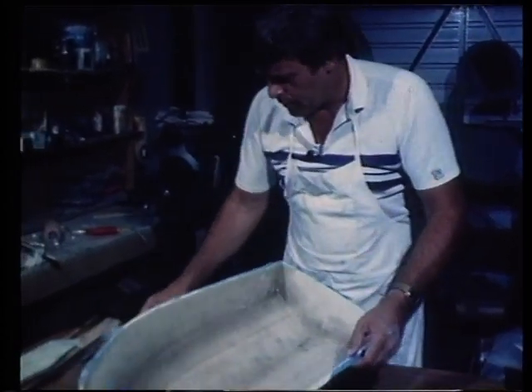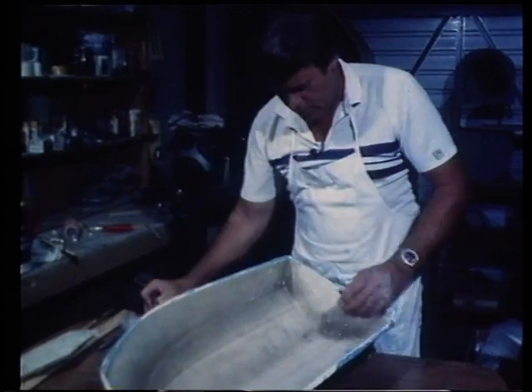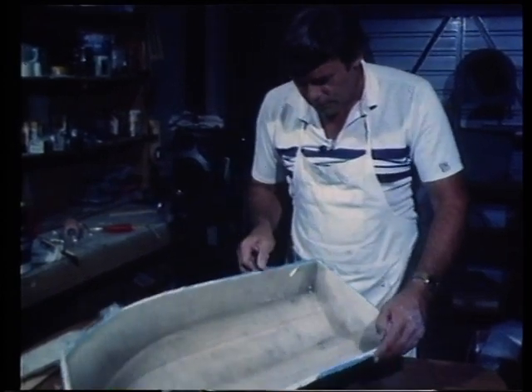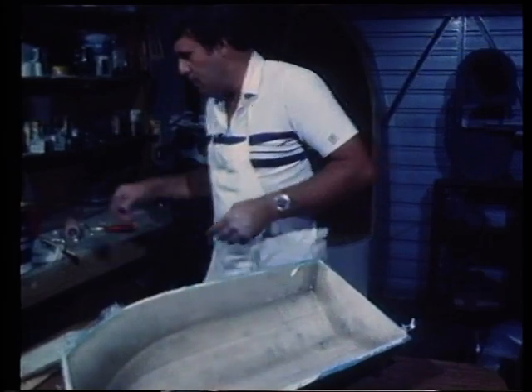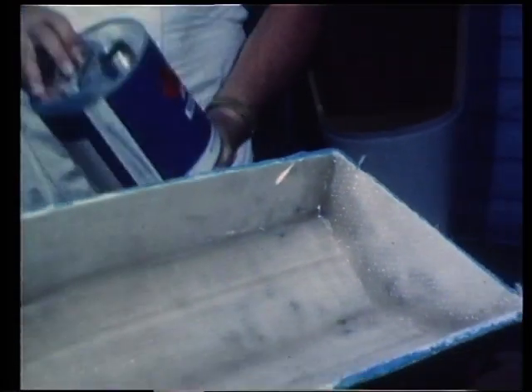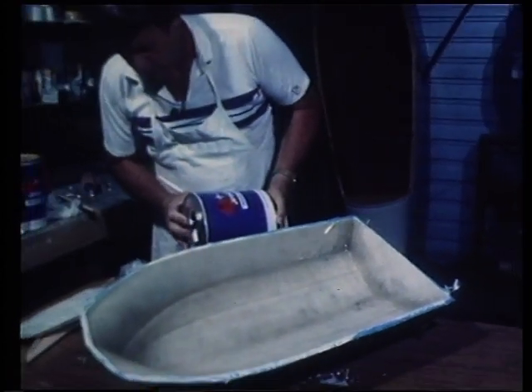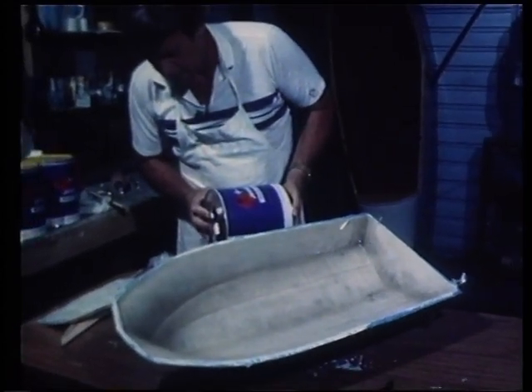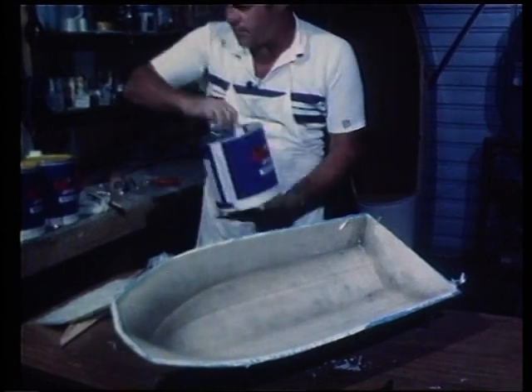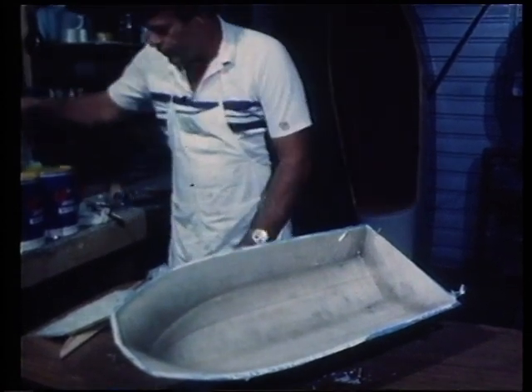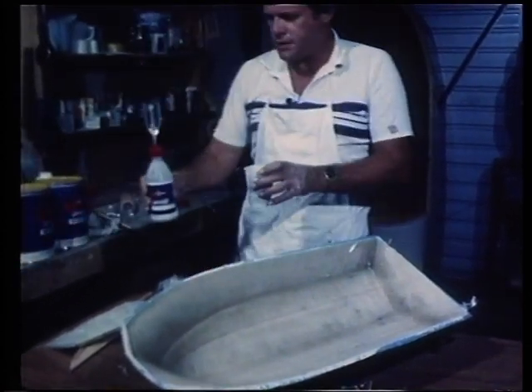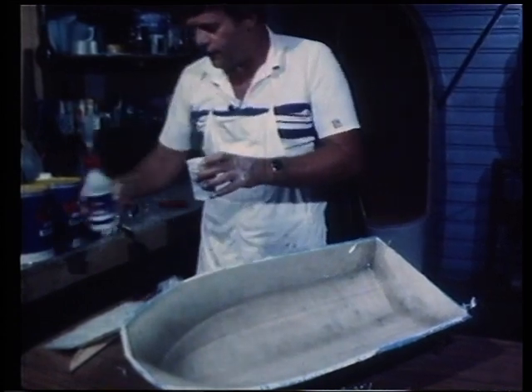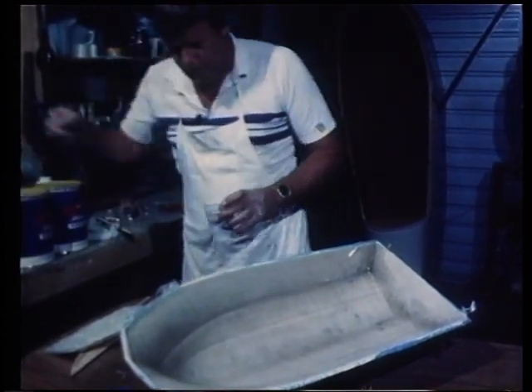Now comes the time when we install the timber inserts, the core in the transom, and also the stringers along the bottom of the boat. Now, we'll need a drop of resin. Heavy core plywood is used for the transom, generally 3/4 of an inch or 20 to 25 millimetres thick. And the stringers are generally made out of softwood. Now, all of those elements will be completely encapsulated in fiberglass, but first of all, we have to bond them